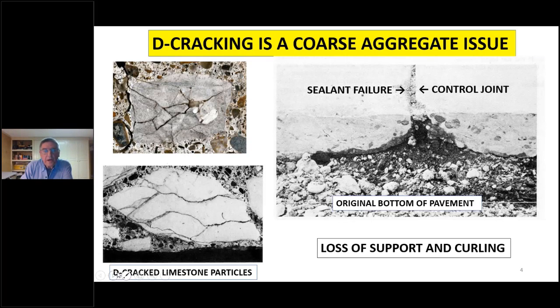As you know, D-cracking is a coarse aggregate issue. Over on the left there, we have a couple. These are about 1 inch maximum size. Typically, it's limestones, sedimentary rocks that are involved. And the cracking that occurs is pretty much like a map cracking, a total shattering of the aggregate particles, which eventually shatters all of the cementitious phase as well. Another picture here shows this cone-shaped type of distress at the bottom, under a joint where the joint has either failed to be sealed or was sealed and it failed. Water ponds at the bottom, and over the years the concrete deteriorates as a result of the cracking in the aggregate particles. Support is lost, and eventually the distress goes up to the surface.